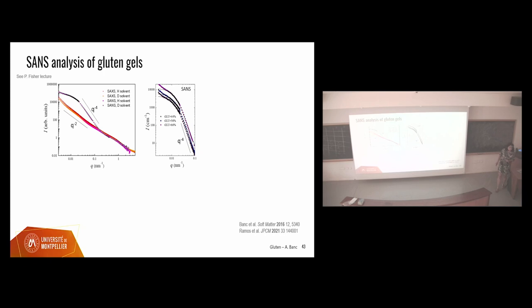We also have a SANS beamline in the lab, so we decided to measure our sample as well. In SANS, if you want to have a large contrast between your protein and your solvent, you have to use a deuterated solvent with your protonated proteins. So we prepared samples in a deuterated solvent.